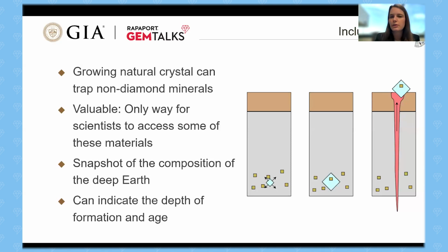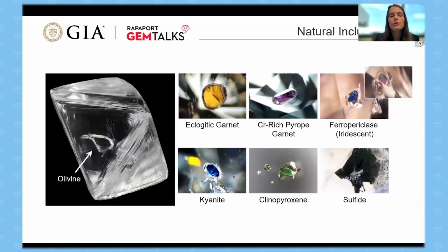So all those numbers that I was giving you before about the age of natural diamonds, that's because people have been analyzing these inclusions. So these inclusions are really quite valuable to us. Natural inclusions, there's a range of different minerals that can be trapped. One of the most common ones is going to be olivine, shown here on the left, which is going to be colorless or potentially have a little bit of a light green color to it. But you can have a range of different types of inclusions here showing different colors.